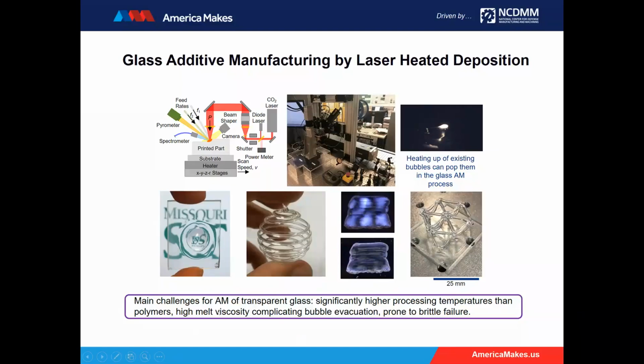And the main challenge of this one is that the processing temperature is higher than polymers, and the viscosity is high, which is good and bad. Good in that it allows you to make a free-standing structure, but difficult for bubbles to evacuate, and also glass is much more brittle.